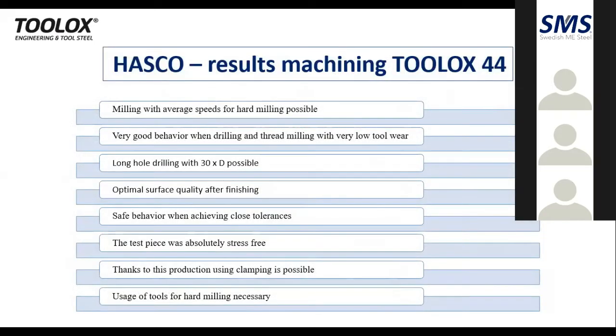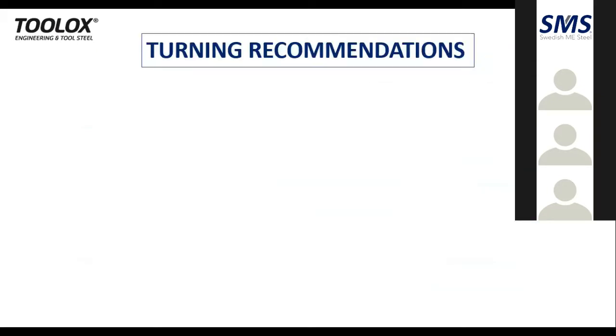And these are some of the machining results of Toolox 44 while they machined the 45 HRC material. They say milling with average speeds for hard milling is possible, and long hole drilling is possible. The test piece was absolutely stress free, the point that we stressed in the previous slide. They also concur with this, Hasco. And usage of tools for hard milling is necessary. So use the right tools, then you will not face any issues machining Toolox.